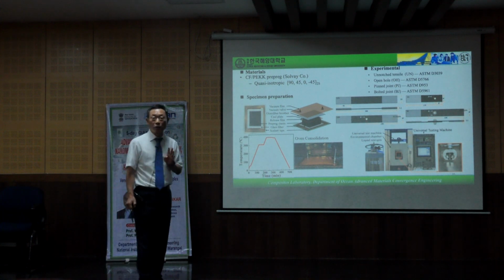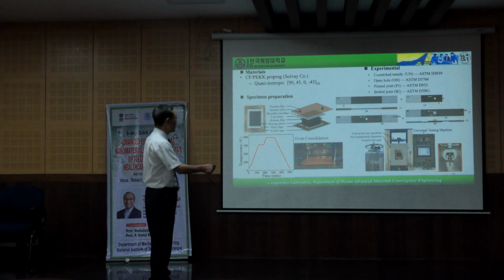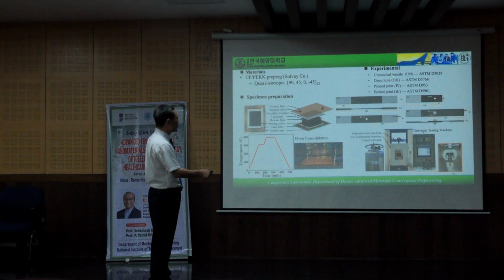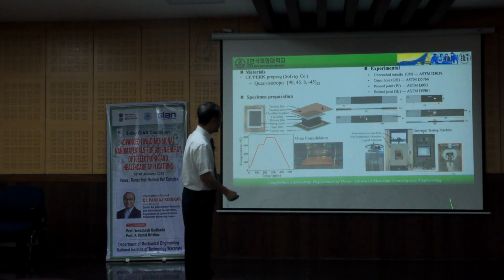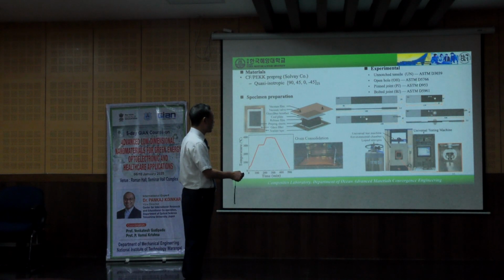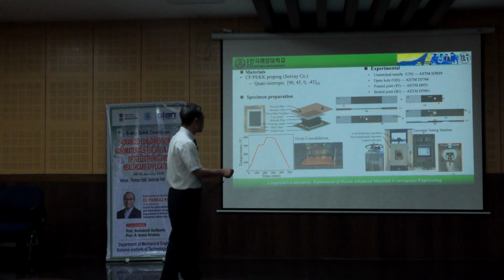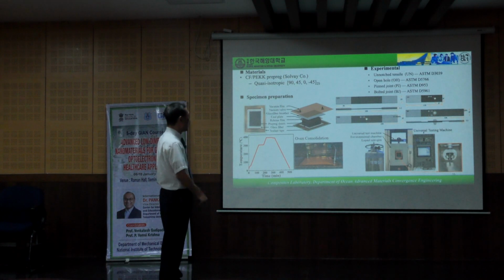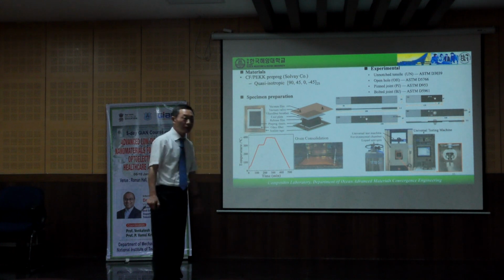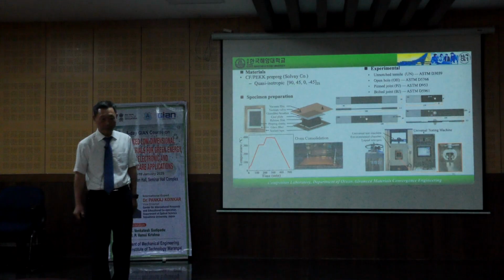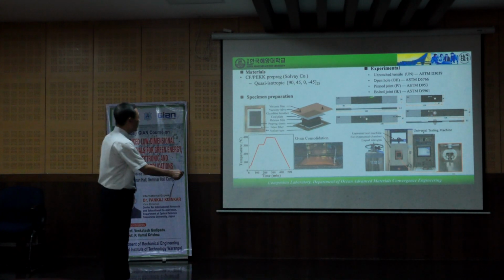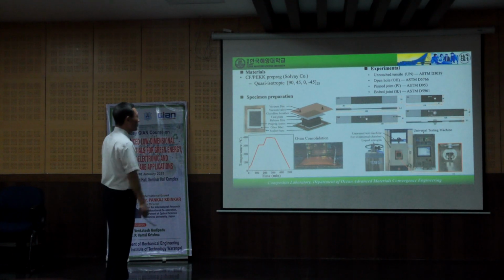We prepared 4 kinds of specimen. First, the unnotched tensile specimen based on ASTM D3039. The second, open hole specimen prepared based on ASTM method, and the pinned joint also based on ASTM method, and the bolted joint based on ASTM method. We prepared 4 kinds of specimens like this: unnotched specimen, open hole, pinned joint, and bolted joint.